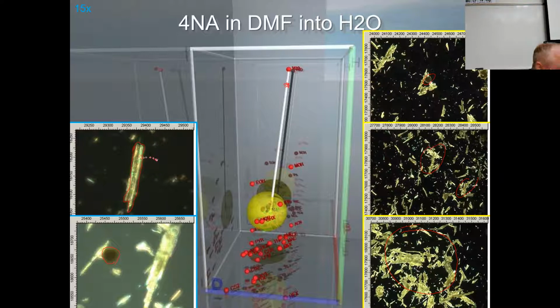And it'll find those edges, and then it can darken them. It can go in and it can fill them, and then it can count up how many pixels are covered with dark pixels, and it can give you some surface area type information. It can measure the length to width ratio, and it can count. So it can give you a histogram of how many particles are in each different category of size. Yeah, that's ideal, to let a computer do your particle counting, because we were about to go blind on this microscope project, but it worked.